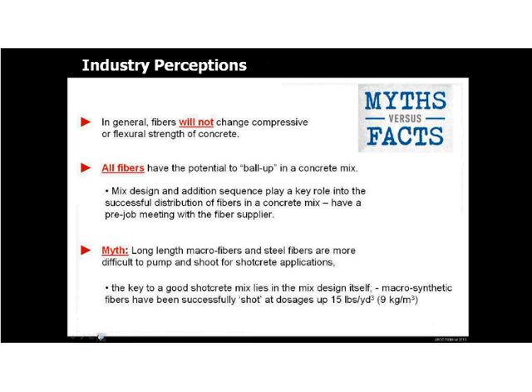Some of the other facts versus myths that I do see and have to answer for within the industry is the use of fibers changing compressive or flexural strength. That is not necessarily an accurate statement. There is data and some research that shows that slight increases in strength can occur. That has a lot to do with how the concrete mixtures are properly consolidated and it's more homogeneous. But in general, as an engineer, I would design my strength around my water-cement ratio.